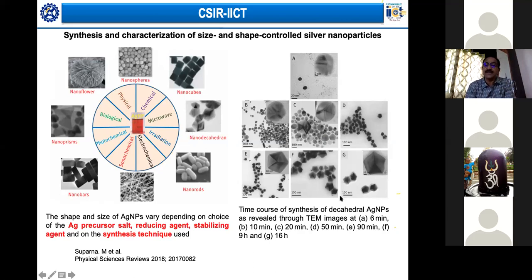Here, by tuning the reaction conditions, they are all decahedral silver nanoparticles with times at 6, 10, 20, 50, and so on. You see that the shape is getting established, very clear with time. So this is the reason people are looking at various routes for the synthesis of the same material, because depending on its shape, the properties or the applications can also differ. That is why they are trying to tune these methods.